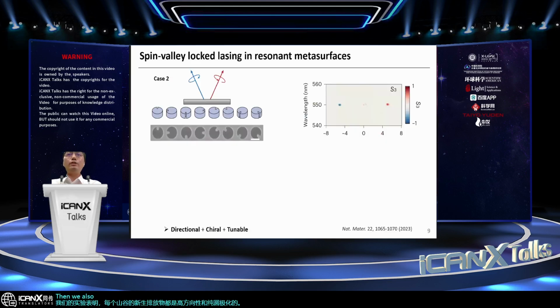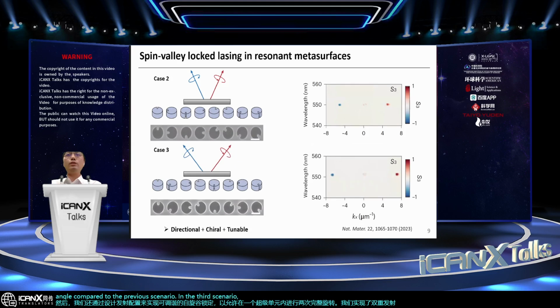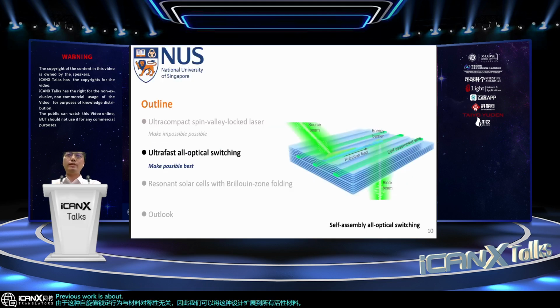Then we also achieve tunable spin-valley locking by designing the lattice configuration to allow two full rotations within one supercell. We achieve a doubled emission angle compared to the previous scenario. In the third scenario, the lattice undergoes three full rotations, yielding chiral emission at a higher angle of 41 degrees. Because this spin-valley locking behavior is independent of the material symmetry, we can extend this design to all active materials.